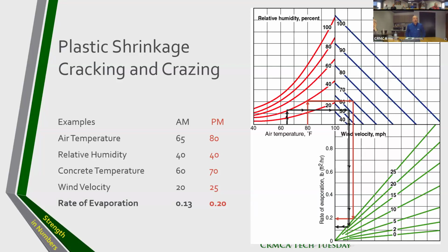Like in the morning, air temperature 65 degrees. So you go up there and then you know what the relative humidity is, around 40 percent. You go across to your concrete temperature, 60 degrees. Now you go down, and the expected wind velocity is 20. Go back to the graph again and you see about a 0.13 pounds of water per square foot per hour evaporation rate expected.